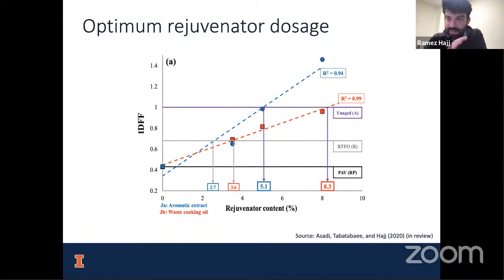And this is really going to be the key to unlocking the use of high amounts of RAP. Right, as I mentioned, we could use 15% RAP without much consequence in the mix, but if we want to use 30%, 45%, 60%, we're really going to have to do something more advanced. And this is one way in which we can do it. So this is the kind of work that we are super excited about, and we think can make a big difference to the asphalt industry.